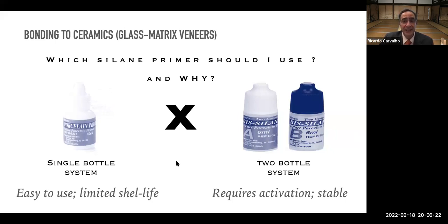How do I know clinically if my silane is okay to use? Well, silane should always be a clean, clear, transparent solution. If I'm using my silane and when I flip the bottle to get the drop and the drop is milky, getting opaque, unfortunately throw it away, because that is already under condensation reaction and no longer provides a good silanization. Okay.